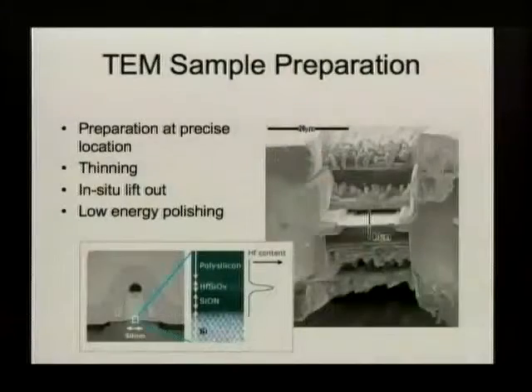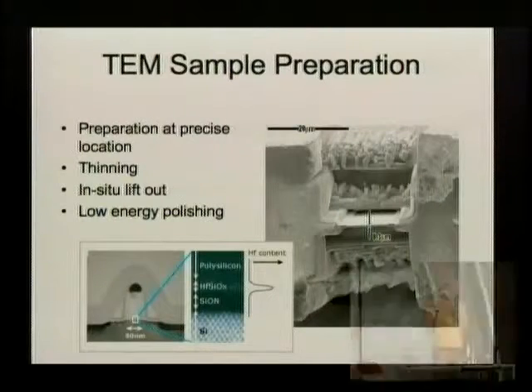So you can, for example, if you have a substrate where you know there's a transistor in the middle, and you have pinpointed that this is the transistor that probably failed, you would like to see why did it fail, what happened. You can use this focused ion beam to cut out the small lamella. Then you would take this lamella with some manipulator, lift it out, put it either in the same device or put it in a different transmission electron microscope, and then you can really see here a slice through the transistor, and you can, if necessary, go down to atomic resolution.